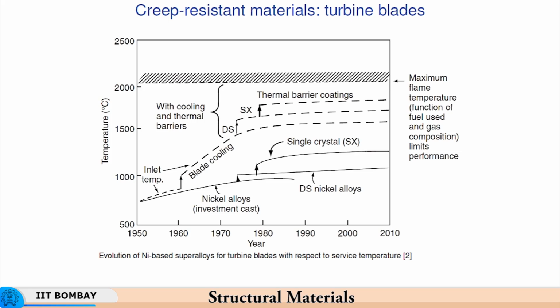So, if the temperature can be maintained lower by blade cooling, then the possibility of creep is that much reduced, because you see that as the temperature increases, the propensity to creep increases very rapidly. So, that is the reason why blade cooling is a very important factor. And then thermal barrier coatings are the ones which bring down the temperature to some extent. Again, they cannot be as effective as blade cooling, but yes, they do bring down the temperature by maybe a couple of 100 degrees, but that will not be again a very significant thing, because a higher effect is produced by blade cooling.